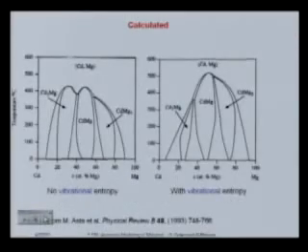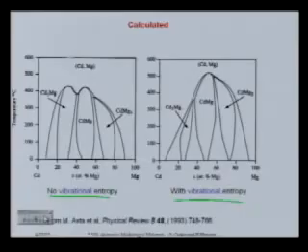So this is the calculation with no vibrational entropy and with vibrational entropy. The first one is the one that I showed you as the standard one. You just take the lowest energy for a lattice model configuration and you do Monte Carlo with that. And this is if you literally do the whole phonon DOS for every configuration. And what you see is that there is some change in topology. Look, at this point it has come down considerably and even has changed the topology somewhat. And usually that's what you'll see. You rarely see new phases, new ground states come in when you include vibrations. But you will change the topology of phase diagrams, for example.